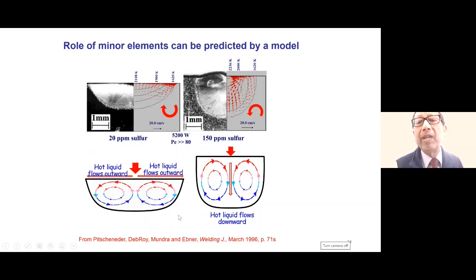And why is this happening? If you also do simulation, apart from doing experiments, you will know the reason. The flow pattern changes. When it has a little more sulfur, the pool is deeper because it acts as a thermal drill. When the sulfur content is very low, the liquid moves from the middle to the sideways, so the shape is wide and shallow. And you can do as many experiments as you want, but you will not know the reason. You will know what happens, but you will not know why. And in innovation, many of the whys are as important as whats, if you want to make use of the scientific knowledge. So simulation is scientific knowledge in digital form.